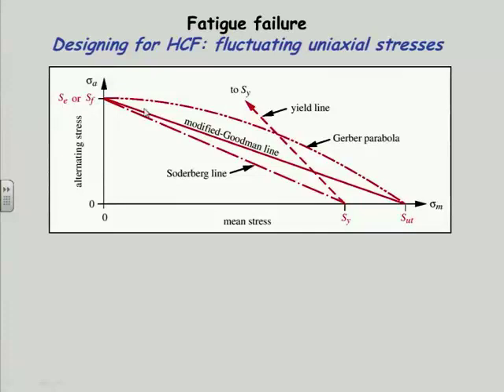And the Goodman line connects to the ultimate tensile strength on the mean stress axis. That, of course, is where the part will break with a static load, right? Notice I also show the yield line here. That's going up to the value of SY on the other axis off the paper. And it's possible that I could be within the Goodman line but outside the yield line. If I had a very large mean stress, I might just yield it on the first stroke, on the first cycle, right? So I need to have that yield line in there.